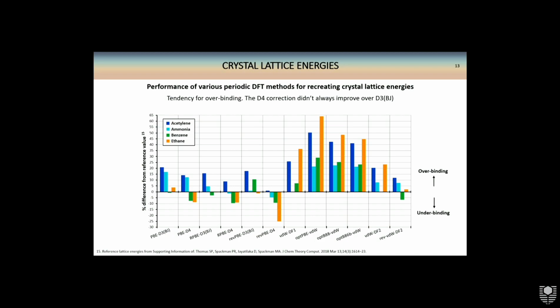In general, we found that there was a large tendency for overbinding, especially in these last six, which are the van der Waals dispersion functionals. And interestingly, the D4 correction didn't always improve over the D3BJ, with the revPBE-D4 becoming quite strongly underbinding for the most part.